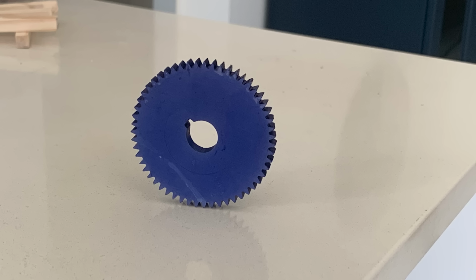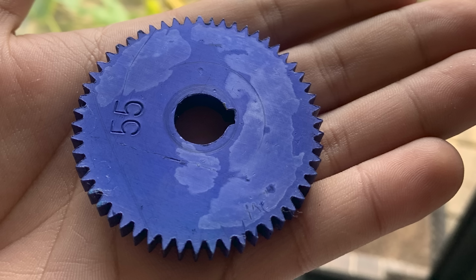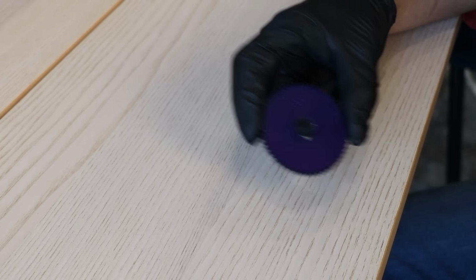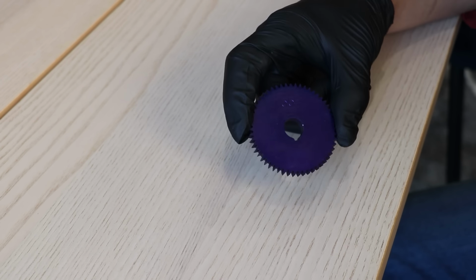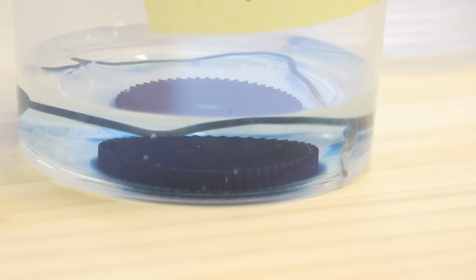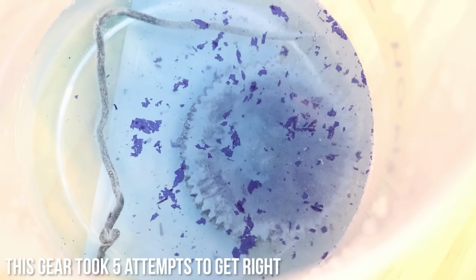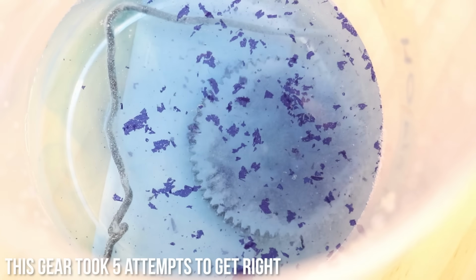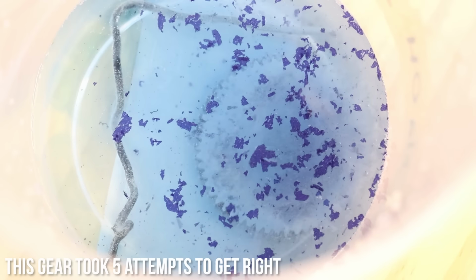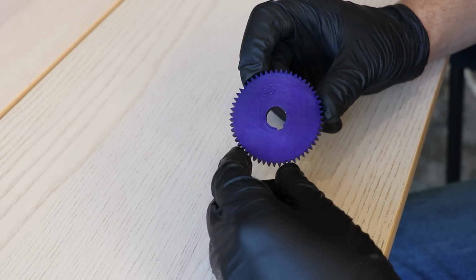The most common source of failure is just not getting the part clean enough, and that will usually show up as tide marks on the part. And at that point, it's pretty much back to square one. Put the part in the sodium hydroxide, let it strip off the coating, and then restart from the beginning. Thankfully though, after about 4 or 5 tries, I got a part that I was pretty happy with.